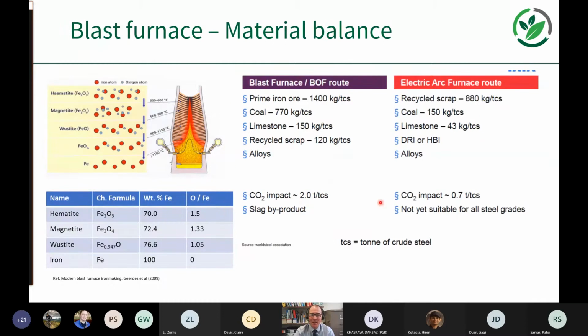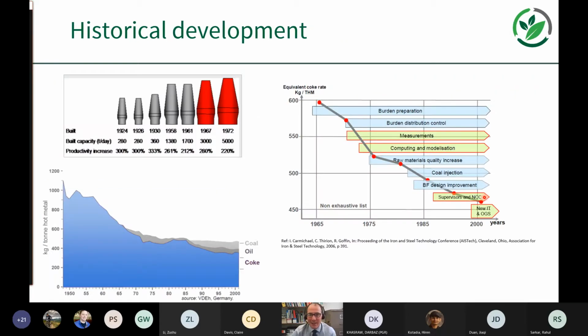And then as a material balance, in the blast furnace you're using around 2.4 tons of raw materials to produce a ton of crude steel. So it requires a lot of materials as well, compared to the electric arc furnace route, which doesn't require anywhere near the same quantity of raw materials. So historically, the improvements that we've seen have all been driven by scale, really. Blast furnaces have increased massively in size. In fact, in 2016, POSCO, the Korean steel manufacturer, started metal production using a blast furnace with an internal volume of 6,000 cubic meters, capable of an annual production of 5.65 million tons. So massive scale. It's an industry that's really improved its efficiency through scale.